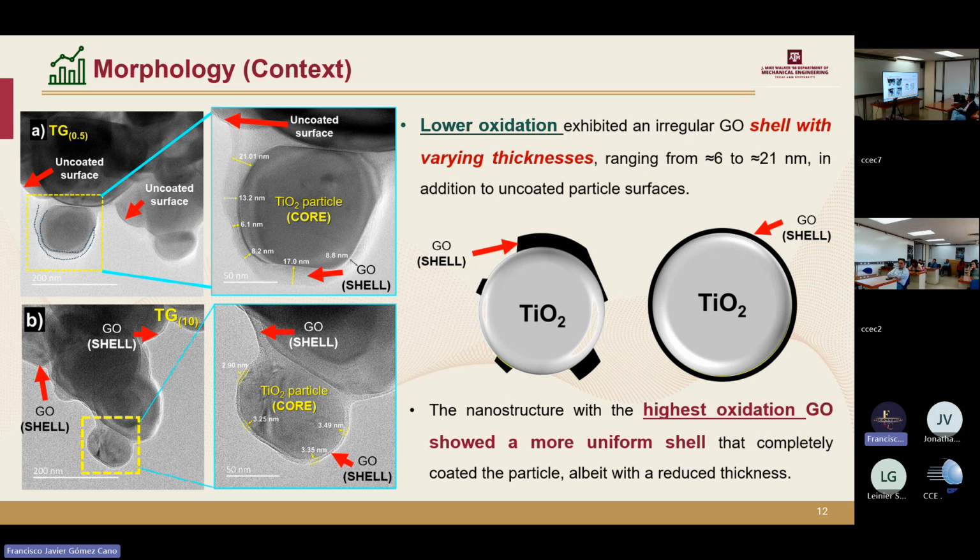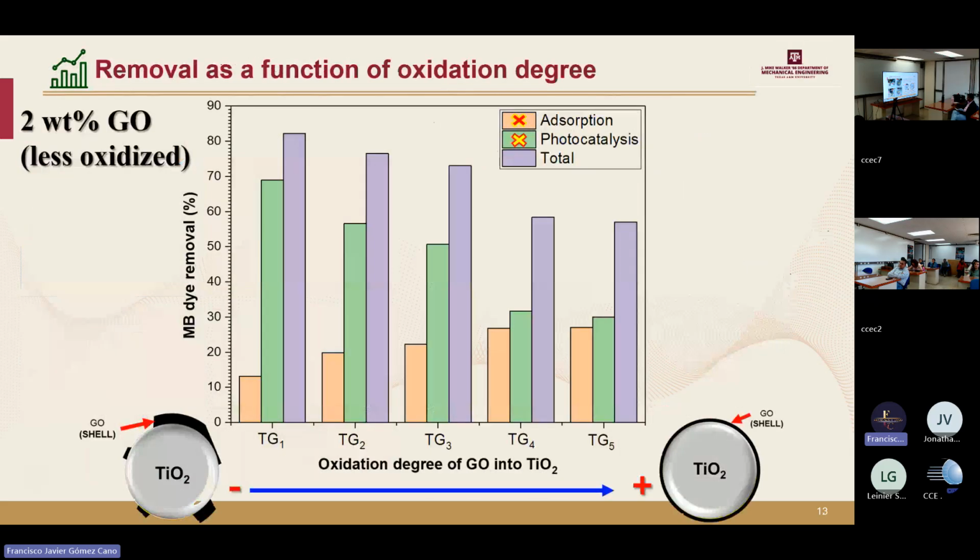This organization was influenced by the initial morphology of the graphene oxide. The graphene oxide with lower oxidation degree shows larger carbon platelets as well as greater stacking compared to graphene oxide with higher oxidation, where there is a higher degree of flaking and wrinkling due to the exfoliation or incorporation of functionalities inside of this material.